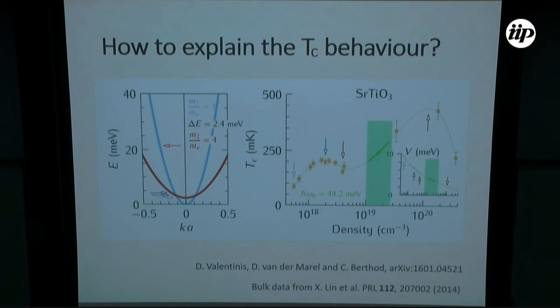And this is what has been done by Davide Valentinis and Christophe Berthod in our department. It's a model based on the properties of strontium titanate and adapted to the interfaces. They have taken the electronic structure of strontium titanate with the two bands and two different masses, and they've taken the relation in the bulk between TC and the density in order to calculate the pairing potential as a function of doping. And here is where the interface sits with respect to the carrier density and so to the pairing potential.